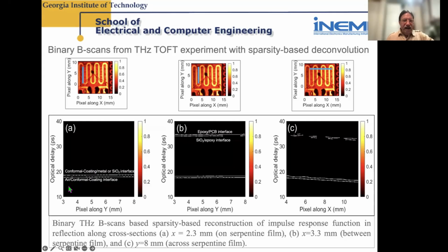So what we see here is the bottom. So the terahertz signal comes up from the bottom and is reflected down. So here we see the air-conformal coating interface. Here we see the conformal coating-metal or SiO2 interface. And we don't see anything up here because the metallization blocks the propagation of the terahertz field any further into the material. Now here, between the metallization, we see the back interface of the SiO2 substrate, or if we go across, we can actually see that shadow effect at different positions. So in all cases, by looking at what happens at the bottom, we can extract the conformal coating thickness.